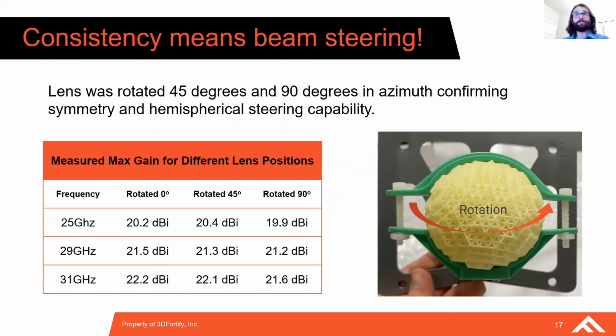The lens was rotated in the mount relative to the feed source to evaluate the performance from several different feed positions. The intent here is to demonstrate one of the unique characteristics of a Luneburg lens, which is the ability to focus energy and form a beam from any position across the surface of the lens. The lens is rotated twice, once to 45 degrees and once to 90 degrees from the original position. The chart shows good agreement with one another for each position and each tested frequency.